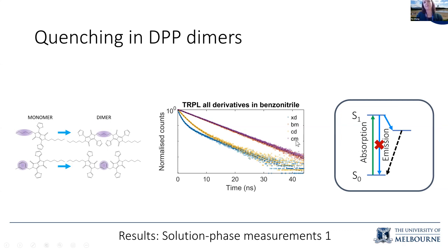fluorescence lifetime, and that in both of the monomers, the benzyl and the C6, they have mono-exponential decay. So that's an indication that the excited state is being depopulated by fluorescence in this case, and that's the only process happening. But you can see that it gets more complicated and further from single exponential when you look at the dimers. And so what that indicates is that where normally you would just have an emission process depopulating the excited state, instead there's this new state that can form that is quenching that fluorescence process. And we want to know what that is. And if it's not radiative, then we have to look at other techniques to identify it.